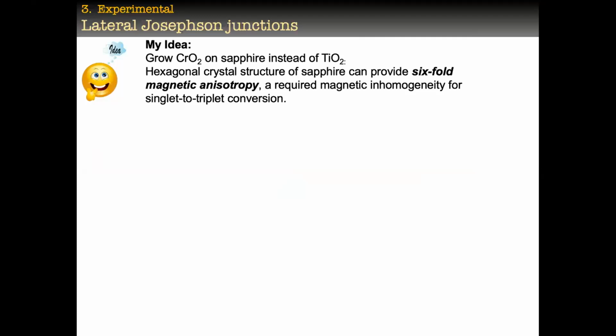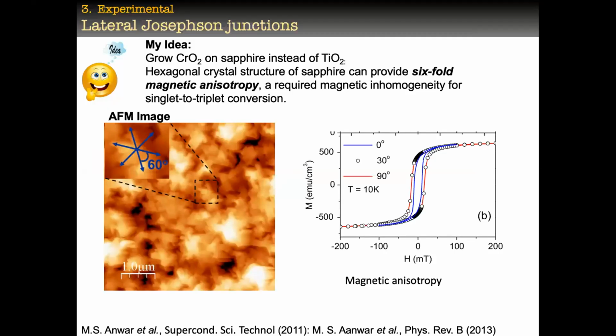On the other hand, sapphire has a hexagonal crystal structure, and this hexagonal crystal structure will give a 6-fold rotation to these grains of chromium dioxide. You see here, it is like a star-like arrangement of these chromium dioxide grains. So now you can see that these grains are in 6 directions. It means the easy axis will be along the longer length of each grain, and we must have 6 different easy axes, meaning the magnetization must be aligned in 6 different directions, and that is giving us the required magnetic inhomogeneity to convert a spin singlet to triplet.